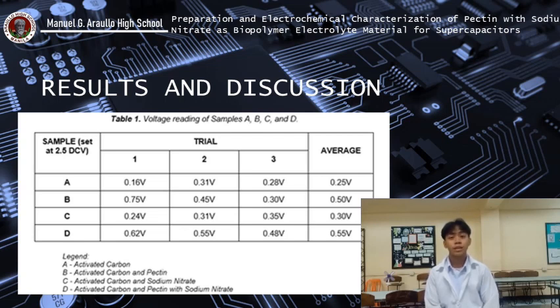Based on the results, sample D, which contains activated carbon and pectin with sodium nitrate, exhibits the highest stored voltage. This result shows how PSN increases the stored voltage of a supercapacitor with AC as the electrode. However, sample A shows relatively lower results than samples B and C. This implies that the PSN as an electrolyte allows more voltage to be stored.